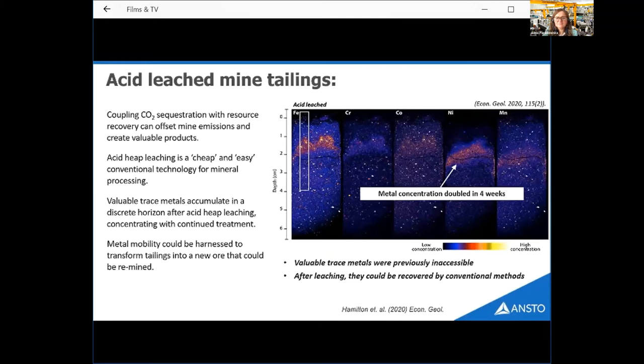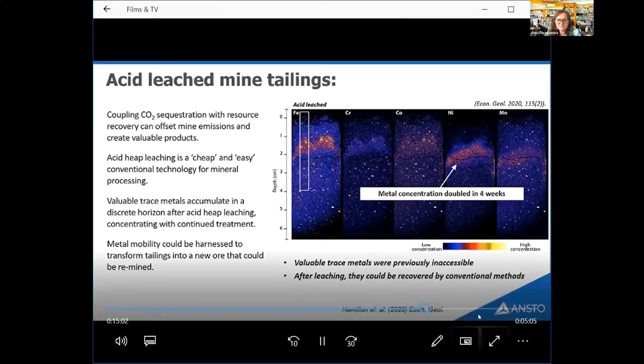And that was really interesting, because these specific tailings had actually been investigated as a potential nickel resource a couple of decades ago. But because the nickel was primarily bound within silicate minerals, which made up the bulk of the tailings, it just wasn't economic to think about as a nickel resource. But after acid leaching, we're showing here that nickel is really strongly mobilized out of the silicates in the top section, and it's being enriched with iron oxides in a discrete zone, which could be a lot more easily recovered and processed.